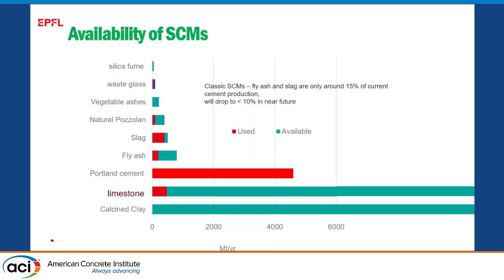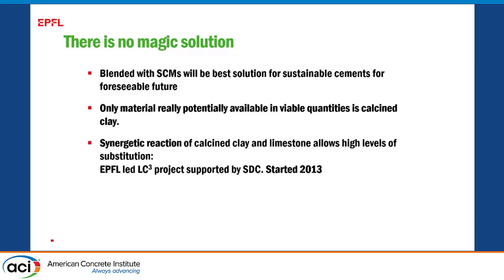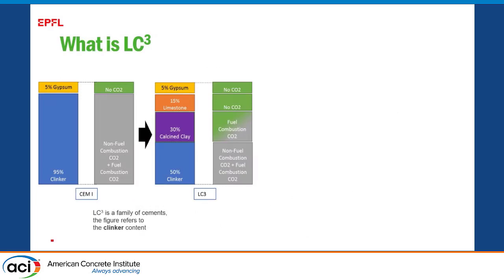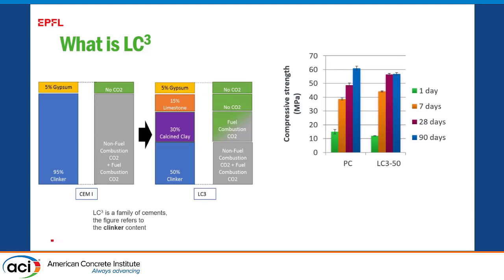So we have a lot of limestone, but we know with the Portland limestone cements that above about 15%, we just get a dilution. So the great thing about LC3 was really the discovery we made quite a few years ago now, that we could have a synergetic reaction between the limestone and the clay. And this synergetic reaction allows us to go to high levels of substitution. So what we're doing here, we're replacing the more carbon-intensive clinker with a combination of calcined clay and limestone. The limestone has pretty much zero CO2 because it's not been through the cement kiln, and the calcined clay has pretty low CO2 because it's calcined at a much lower temperature and there's no process emissions. But here, even with this 50% substitution, you can get the same performance as Portland cement within 7 days. And that's the secret, because you cannot do this with other SCMs.